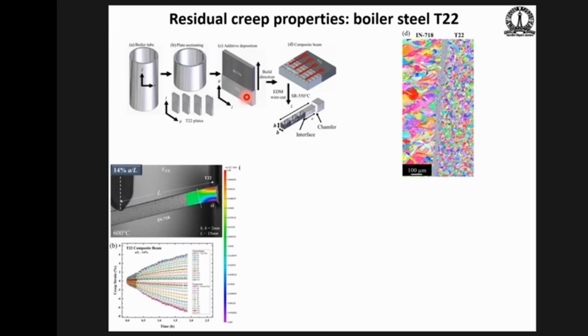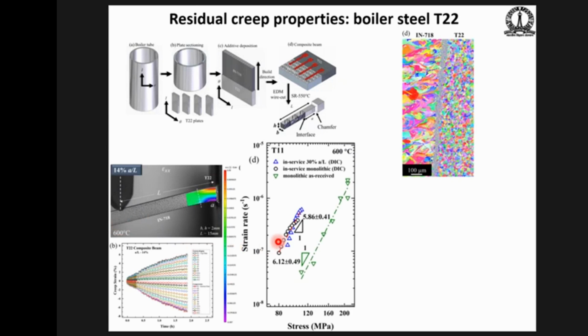And so one can, again, start doing experiments where you recover the strain as a function of time, except now part of this is your sample and part of this is inconel. So this is what you get. Whether you have a monolithic material or 30%, that is, the length of the cantilever is 70% inconel and 30% sample steel, your data more or less collapse onto the same line. And there is a factor of 7 or 6 or something increase in the creep rate with respect to the virgin material, which was put into service 27 years prior.